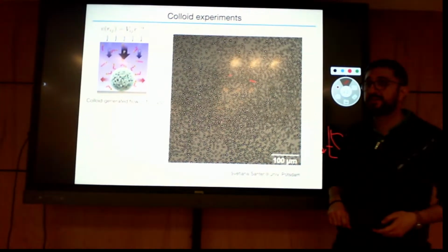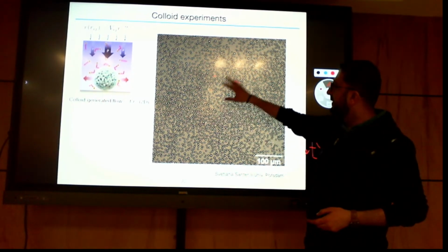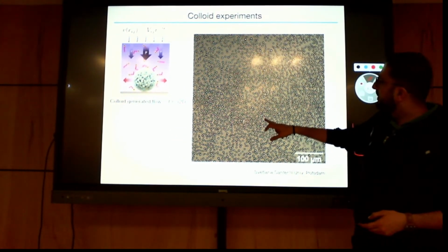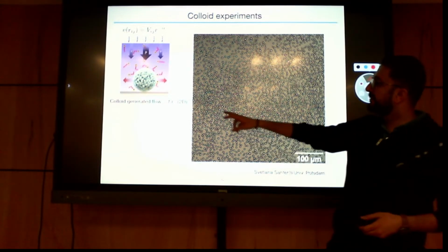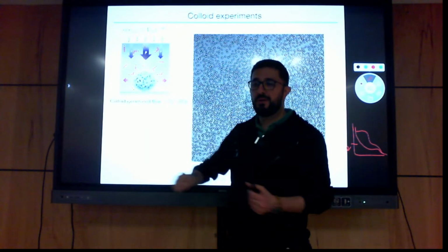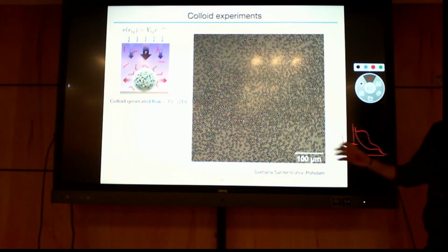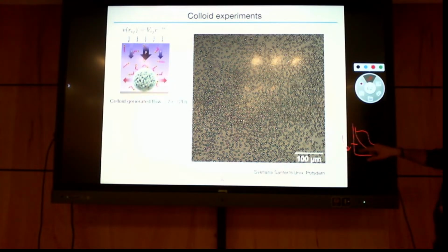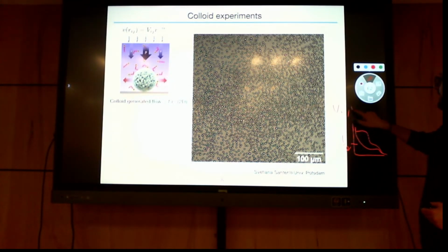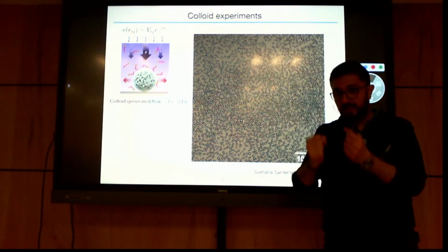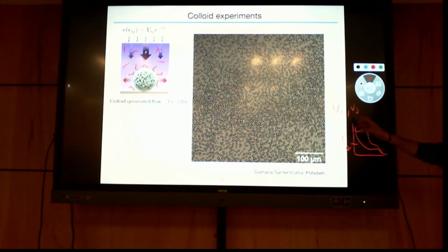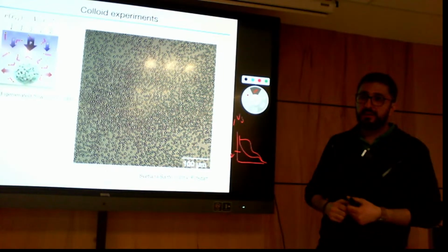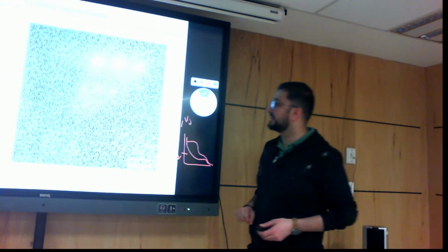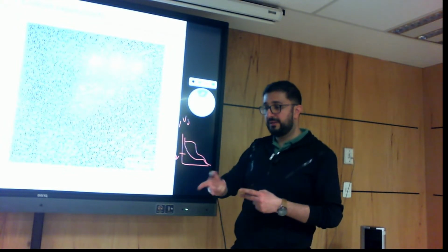Now comes where the polydispersity comes in. You look at this picture, you see particles of different sizes. Particles of different sizes means a different strength to push the colloids. Now that's not exactly my model, because that would be my model if I take Vi and Vj, so each particle has a different amplitude to push the flow. But if I take this, I have a problem in the simulations: they cluster together, so that you get this polycrystalline state, you don't get a glass. But the motivation to take interaction polydispersity comes from these experiments.